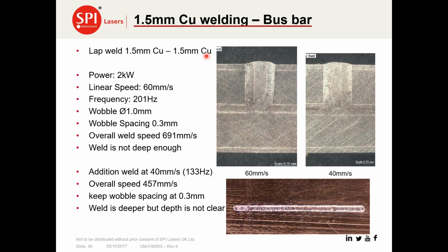Here are some examples of busbar welding, copper. So it's 1.5 millimeter to 1.5 millimeter using a 2 kilowatt laser. What you can see is we can achieve, by using this oscillation technique where we're moving the laser round and round, an almost square weld profile with a well-defined bottom section, which is pretty flat. There is a little bit of protuberance there, but it is quite minimal, and we can focus it pretty much to the depth at which we have the interface or the joint in this particular lap weld. And we can control the melt formation, and as a result, the amount of spatter that is generated.